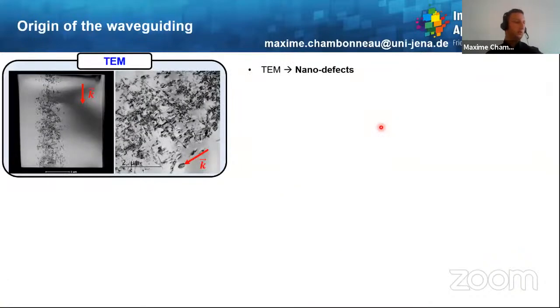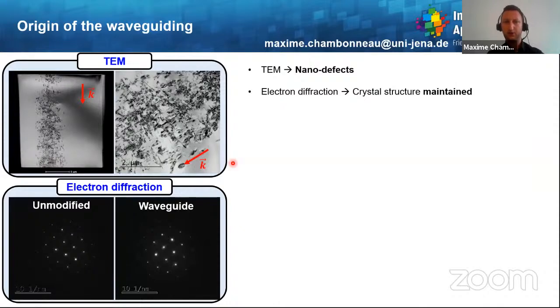Then one question is, what would be the origin of the waveguiding? To answer this, we relied on nanoscale characterizations, especially with TEM, transmission electron microscopy. As you can see here, it is possible to image some nano defects along the waveguide track. What about electron diffraction? We have carried this out, and as you can see here, there is no drastic change in the crystal structure. The crystal structure is maintained, but still we see under bright field TEM that there are some defects.